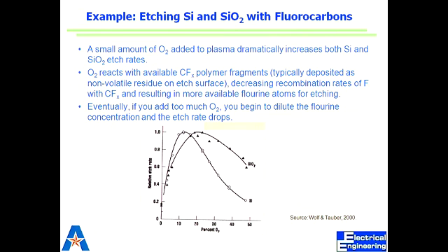But the difference starts from here. F by C decreases, so what do you think about the etch rate? When F by C decreases, the etch rate should also decrease. I told you it's a general law that the higher the F by C ratio, the higher the etch rate. So the etch rate decreases. But does it decrease for both silicon and silicon dioxide, or only for one of the two? That's the difference. It decreases only for silicon. Not for SiO2. That's actually the point.